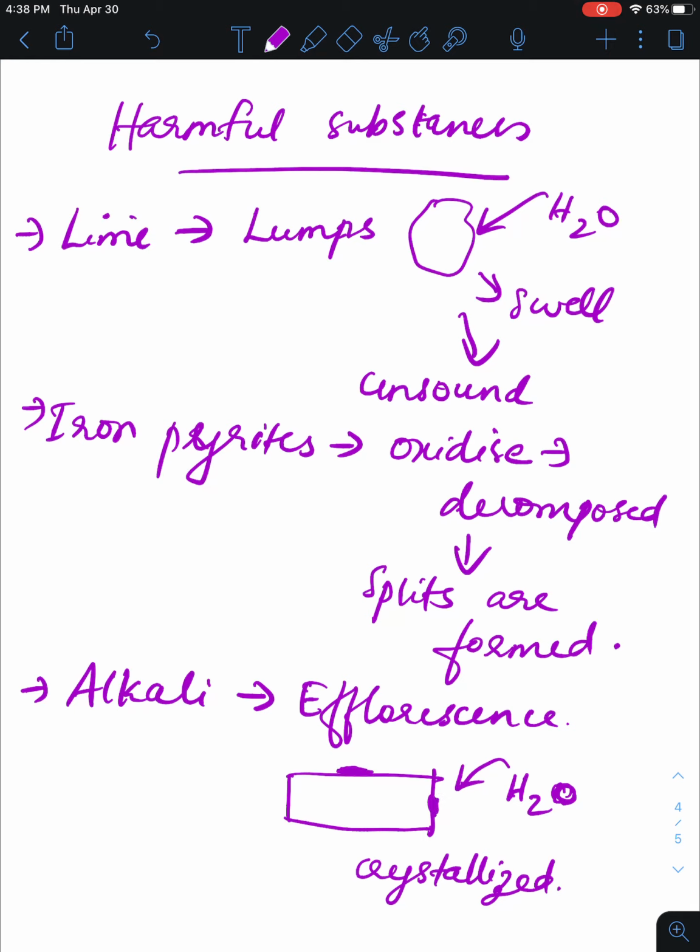During masonry, when the work is done, we pour water on it. At that time we have to make sure we provide only enough water so that the mortar becomes strong. We should not pour excess water on the brick, otherwise the efflorescence will increase. We should remove it with a dry cloth or dry brushes, and not wet it again to clean it, otherwise the crystallization and efflorescence will increase.